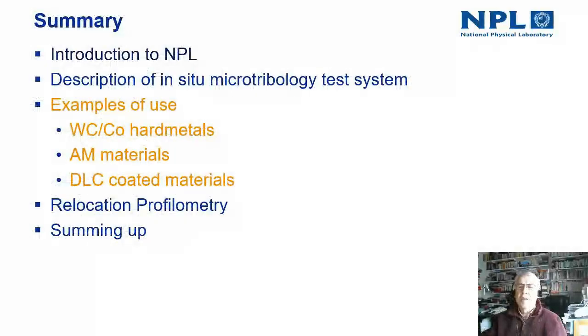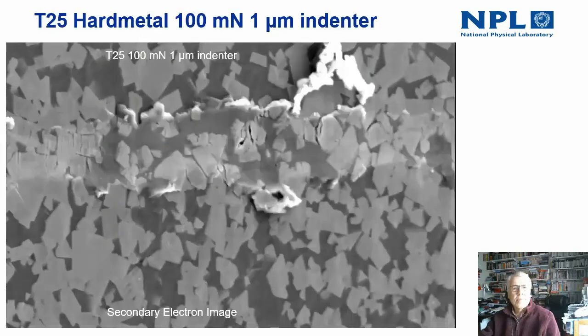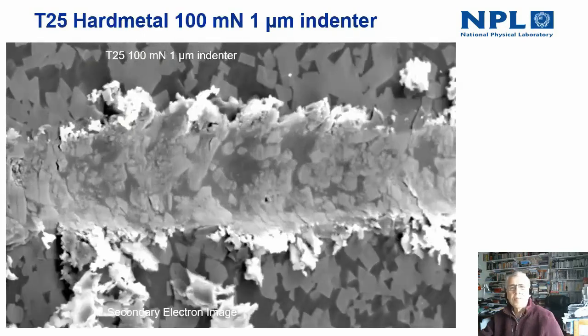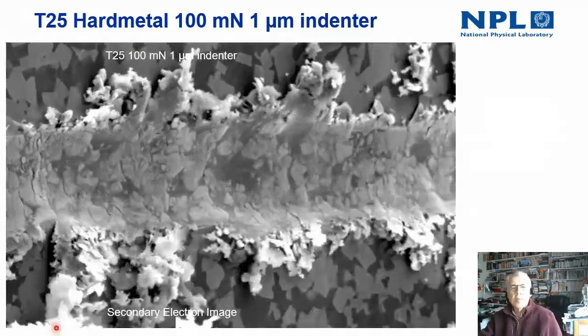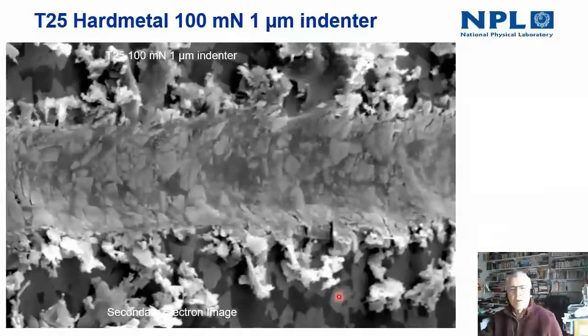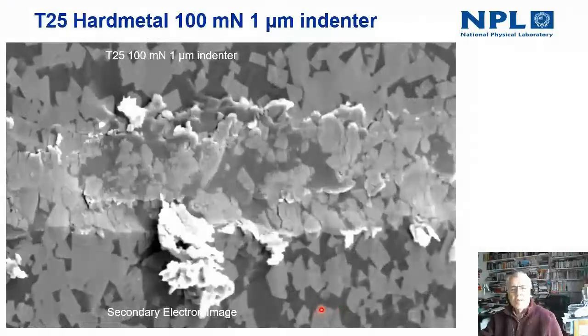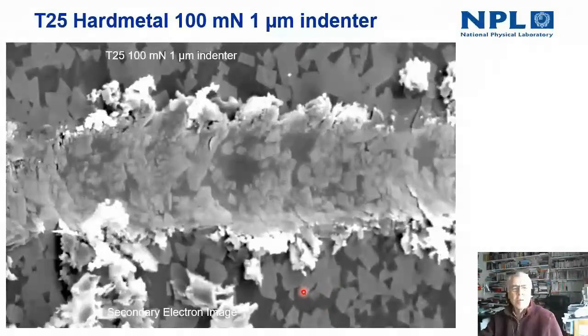So I'll now explore the use of this equipment with examples on 3 different materials: tungsten carbide cobalt hard metals used as tools all over the place, additive manufactured materials which are of current interest, and DLC coated materials. So in this first example, this is a tungsten carbide cobalt, and you can see the typical structure in the regions away from the scratch of tungsten carbide grains embedded in the cobalt matrix.